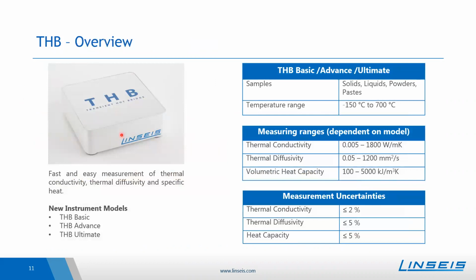So the transient hot bridge instrument allows fast and easy measurement of thermal conductivity, also thermal diffusivity, and the specific heat capacity by calculation with density, of solids, liquids, powders, and pastes in a very broad temperature range from minus 150 degrees to 700 degrees Celsius. You can see it also here in the thermal conductivity range that it allows the measurement of a lot of different materials. The instrument is available in 3 different models. The difference between those models, so the basic, advanced, and ultimate version, is the range of thermal conductivity which can be realized.